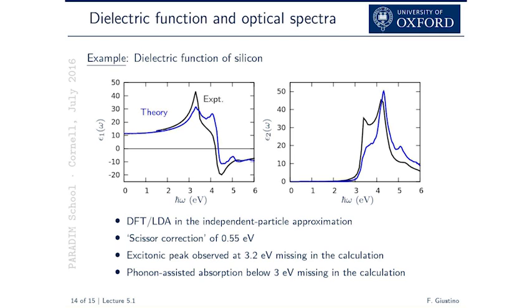And the other thing I would like to mention is that in this picture, in the case of silicon, as Darrell mentioned, this is an absorption which is at the direct onset. Okay. So if we go back to this, the onset seems to be around 3 eV, but the gap is actually, in experiment, 1.2 eV, here it is 0.6 eV. So it should be possible to absorb something here. Okay, so that is in Kittel's book what is called the indirect absorption, and it requires phonons.